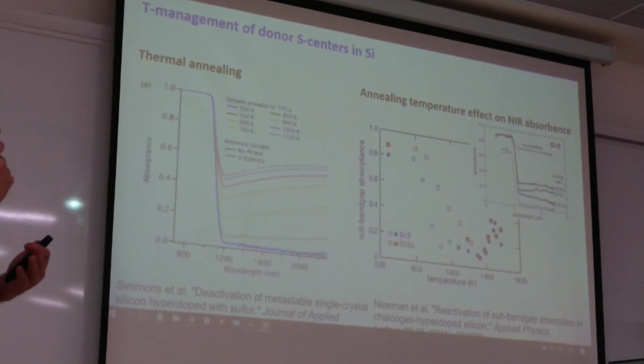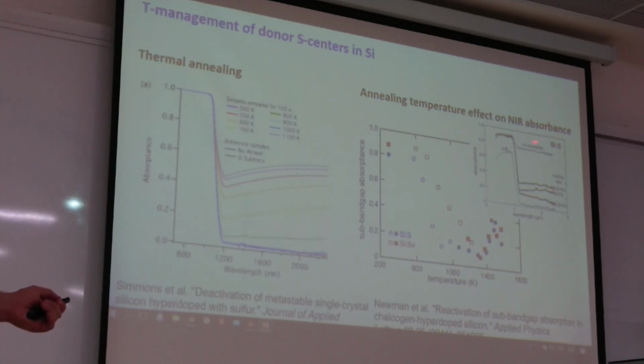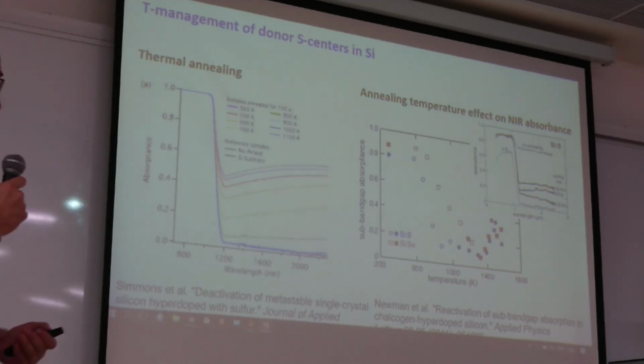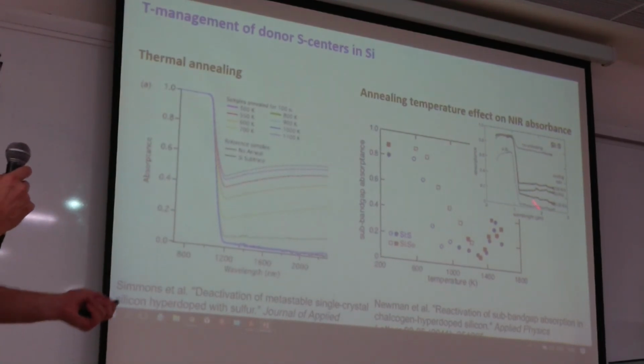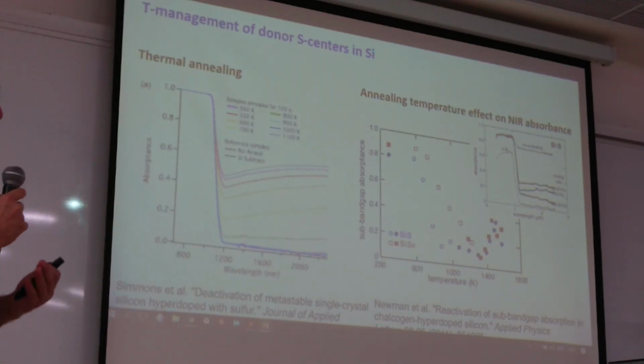And so this story continued with optimization. People looked at how the absorbance in the infrared range, between 1 and 3 microns, changes versus temperature, and found that there is a strong minimum at high temperatures, which are typically used for annealing. So thermal annealing looks very bad for this kind of infrared absorption. It just cancels the effect of doping.